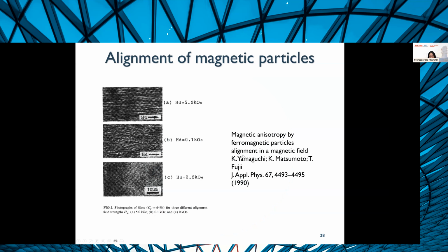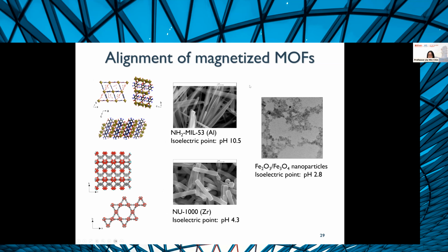So in this case, these authors took some ferromagnetic particles. This was quite a while ago, hence the quality of these images, but they controlled the orientation and alignment of their particles using a magnetic field, but they used ferromagnetic particles. Now, a clear and obvious limitation here is that you need ferromagnetic materials, right? Most MOFs are not ferromagnetic. So then the question arises, how do we use MOFs even if they're not ferromagnetic and use this magnetic field alignment to control them? And so one strategy to do this is to magnetize the MOFs.